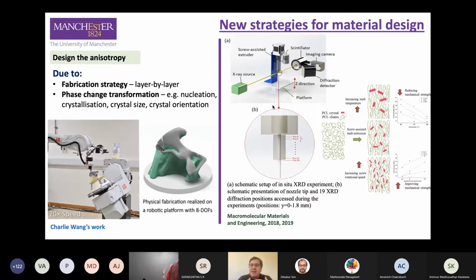So the impact of these processing conditions in terms of nucleation, crystallization, crystal size, and crystal orientation. And of course, the correlation of these morphological changes and the final properties of our part, allowing us, by changing the processing conditions, to design the anisotropy of our printed parts.